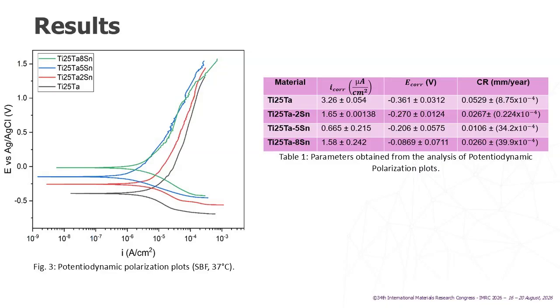The curves of tin-containing alloys, which are shifted further to the left with respect to their current density, indicate that lower current density values can be achieved, which would imply a lower corrosion rate. The table shows the parameters obtained from the analysis of the polarization curves.